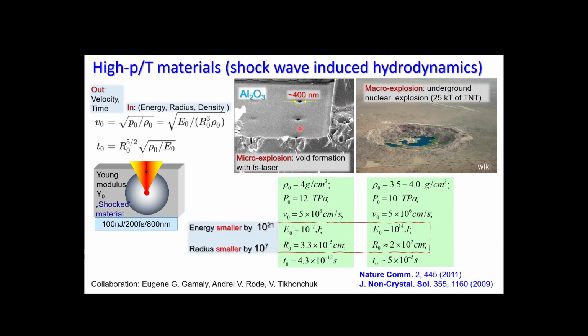So somehow, this is not that we are proving we have the same event here, but just to see on the tutorial level, with simple formulas, that energy deposition to the very small nanoscale can be very efficient, and the energy density is huge. So we expect that modification around this region where the shock wave is modifying the region, which is actually not necessarily irradiated with the femtosecond laser, can be very high. So we can expect to see high pressure, high temperature materials in this volume, and this is already observed and reported. But this is for another day to discuss.